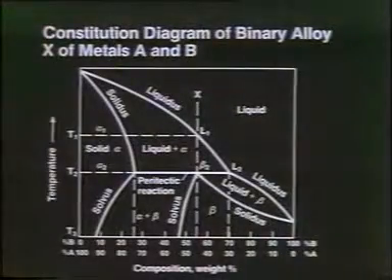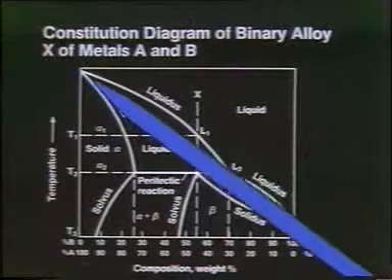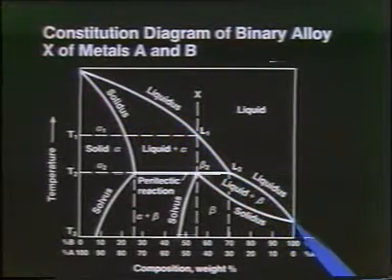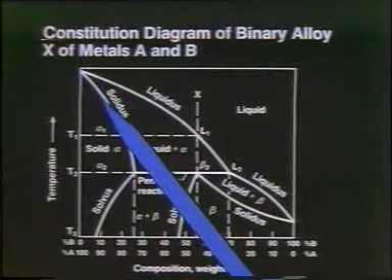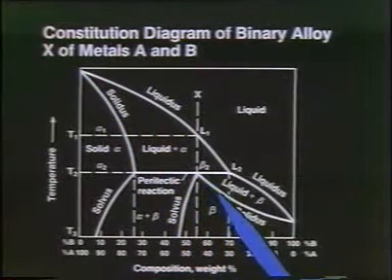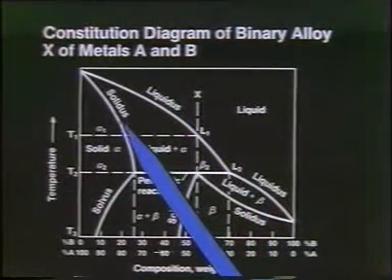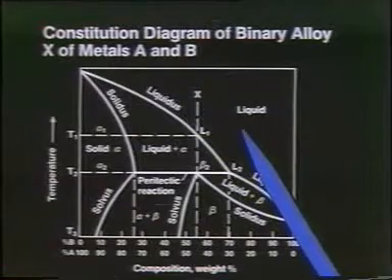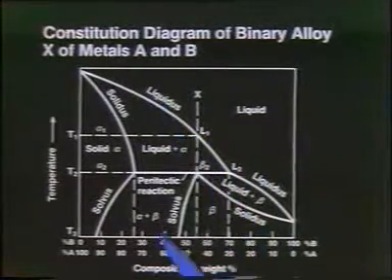We have other kinds of diagrams. In the next slide, we see a diagram called a peritectic diagram. Again, we're going to have things like the liquidus line — everything above that is liquid — and we have the solidus line. Between the liquidus and solidus, we'll always have a mixture of two states: liquid and a solid. So it's going to be this solid solution, which is alpha, and this liquid over here, the composition of which we could determine for any composition in between.